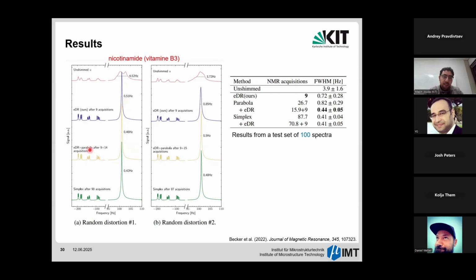If after that we apply a parabola optimization algorithm that's also used by commercial systems and requires 14 extra acquisitions, we can get 0.4 hertz line width. And compared to the simplex that takes 90 acquisitions from here to here, we are not too far. So already with the AI model, we can get 0.5, which is quite close to what the simplex can get in 90 acquisitions. Or if we apply the parabola after the AI model, in a total of 23 acquisitions, we can still get almost the same shimming quality.